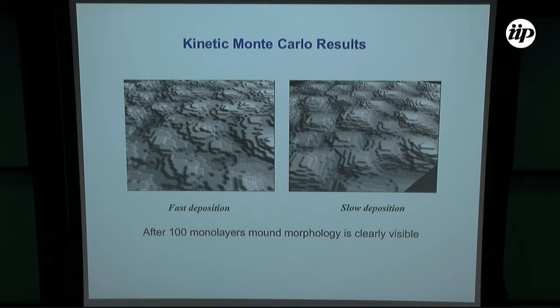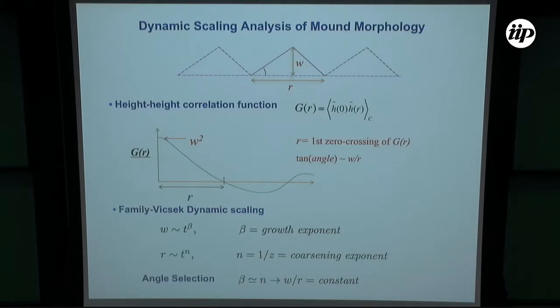So how do you analyze this surface morphology, this island morphology? Because it's a little bit different from what I showed you before, but the same idea of dynamic scaling applies to this as well, with a slight change. The change is that now we have something else that is evolving, namely the width of one of these mounds. So if you think of these mounds as something looking like a triangle, the height of these mounds is the width W that I was talking about before, and the width of the mound is a length R. Both of these now grow with time, and this is nothing but the parallel correlation length, so it has an exponent of 1 over z, and because here they're running into each other and coarsen, borrowing the language of equilibrium coarsening problems, you can call the exponents. The literature switches back and forth, so I give you both, that you can call this thing n.